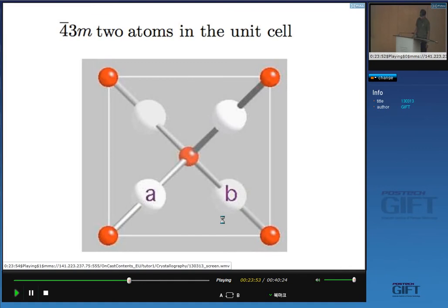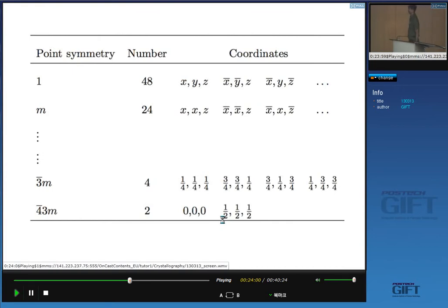Now, obviously, this requires a lot of thinking, and a lot of people have done a lot of thinking on your behalf and produced tables like this. So for every single space group, 230 of them, this is really a very simplified table, but you can look at the point group symmetry of every location inside the cell. So obviously this is a completely general location in which there is only a one-fold axis. That means rotate by 360 degrees. So there's no significant symmetry there. If I place an atom at a completely general position inside the cell with this space group, the space group PN bar 3M, I will have 48 atoms inside the cell.